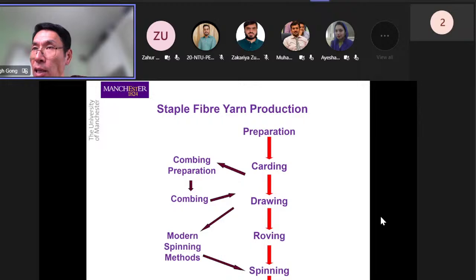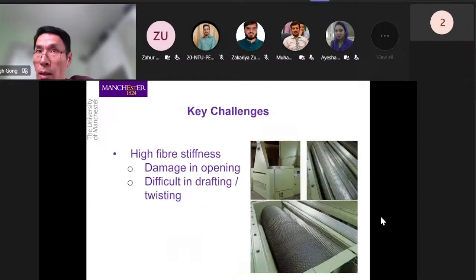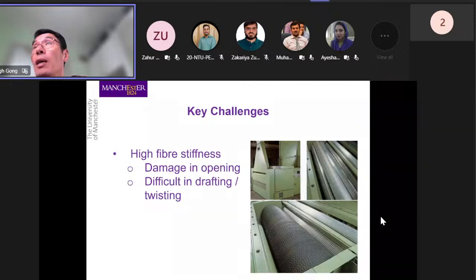As I already mentioned, these mechanical processes cause fiber problems and process problems, because these carbon fibers, as I said, generate dust material. And the opening devices tend to be very vigorous, and they will damage the fiber, and they will generate lots of this dust material, which needs to be strictly controlled. I guess this is dependent on where you operate. In this country, we certainly have a lot of difficulty, and we tried to build a lab to do this, and it became almost impossible in the end. So we have to take an alternative approach, as I will describe in a minute.